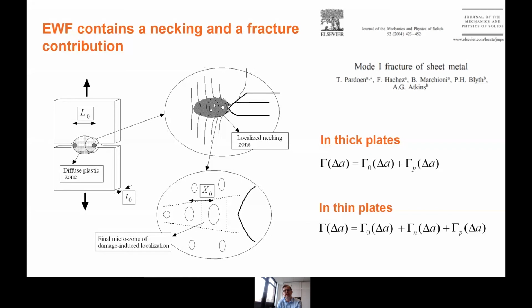And as a matter of fact, if you look from the perspective of the J integral, or from the perspective of the essential work of fracture, let's start with a thick plate. In a thick plate, you basically have your total work, which I call here capital gamma, is the sum of the work spent in the fracture process zone, which I call gamma 0, plus gamma p, and gamma 0 is essentially related to the work spent for growing voids at the crack tip. But in thin sheets, as you see below, now you have an additional contribution, gamma n, the work spent per unit area to neck the material in front of the crack.